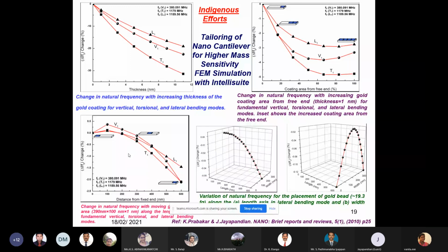We monitored by a thin coating on the cantilever, copper coating or gold coating. Here, a gold coating on the cantilever. Is there any variation in the resonance frequency? This is to get higher sensitivity mass measurement. In our laboratory, we tried the same way on the right side: instead of fully coating, partially coating from the fixed end to the free end, with a 1 nanometer thickness, a small piece added. These are all tailorings of the cantilever. Is there any change in resonant frequency, for very high mass sensitivity? Mass sensitivity means del F by del M. A small change in mass causes a small change in frequency, del F by del M. That is the mass sensitivity.